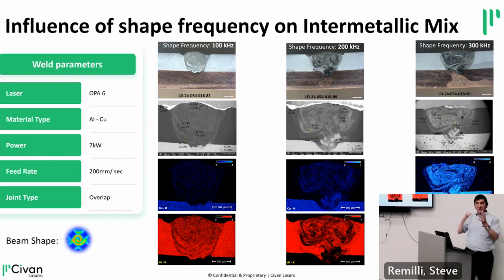In the EV, when you have the batteries and you have the bus bar, there are many times you want to connect copper to aluminum, but the electrical conductivity and the thermal conductivity have to be very good. But if you have intermetallic mixing, if the copper and aluminum mix with one another, two bad things happen. First of all, the thermal and electrical conductivity is poor. And second, it's a very brittle phase of the metal. And then when you put it in the car and the car shakes for 200,000 kilometers, eventually it's going to break. So welding copper to aluminum without intermetallic mixing is critical.